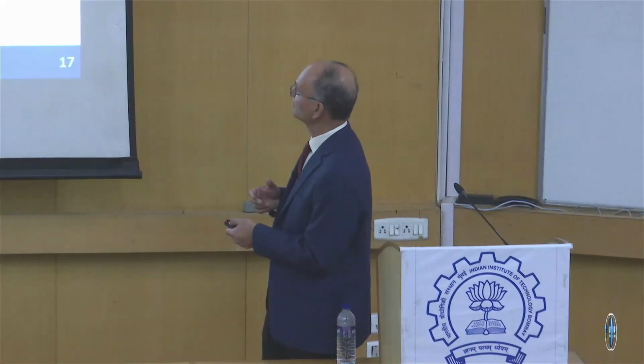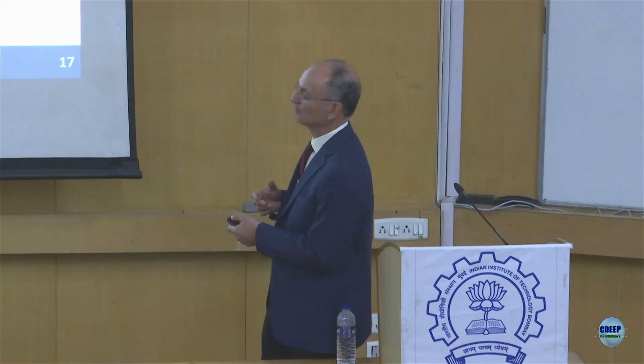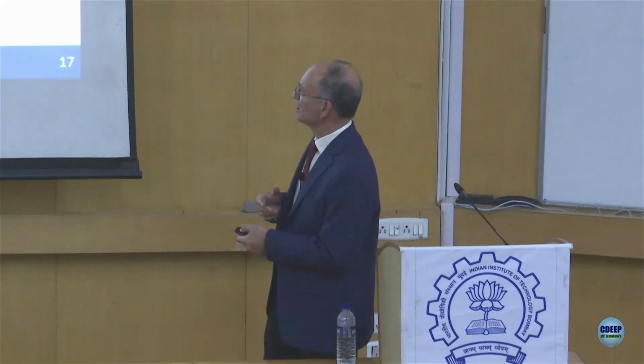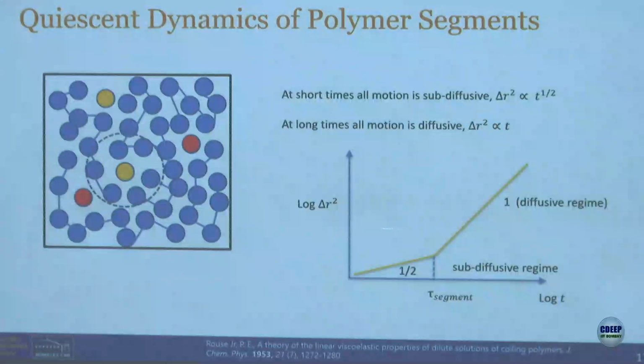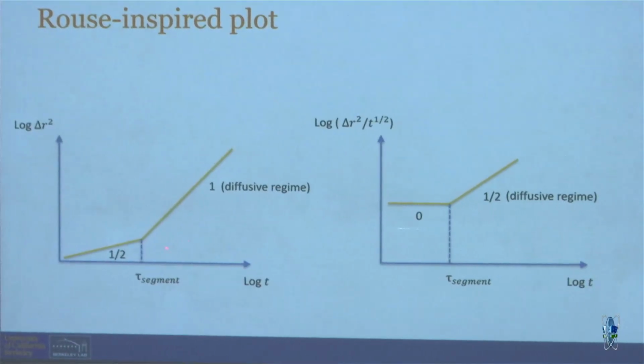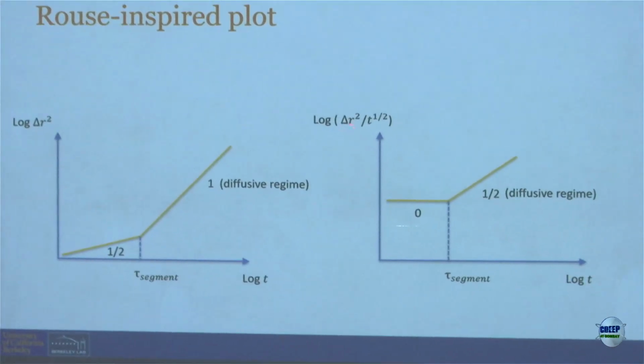And in polymers, this subdiffusive regime is known to have a power law of a half. So we expect the mean square displacement in the subdiffusive region to go as t to the half power, not t to the 1 power. And so instead of making these kinds of plots, I'm going to show you, for convenience, I'm going to divide by t to the half so that when I get this subdiffusive motion, it's a plateau. And you don't have to try and determine scales by looking at slopes. Okay? It just makes it simple.